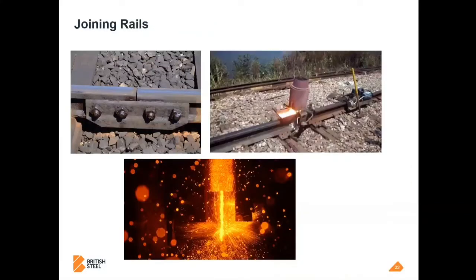So while we're talking about welding, we should also just quickly talk about jointing of rails. So traditionally, rails were joined by bolted joints, fishplate bolted joints, as you can see in the top left there. The trouble with bolted joints is you get a lot of dynamic loading. You recognize the clickety-clack sound from a bolted railway. That distinctive clickety-clack is actually battering the rail end. You can perhaps see on the left hand rail at the top there, there's a bit of a lip on it where it's been hammered by hammer blows by each axle that passes across it.